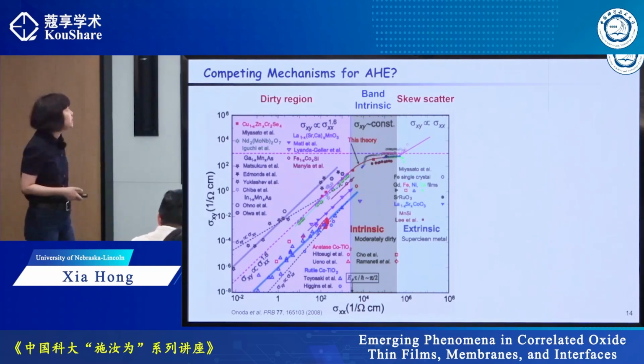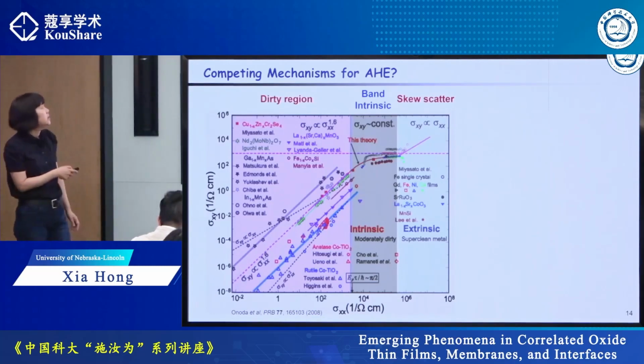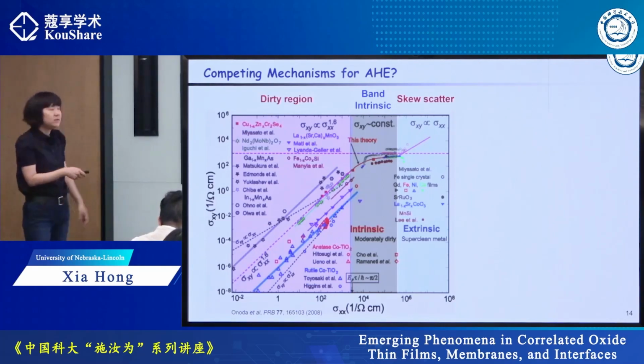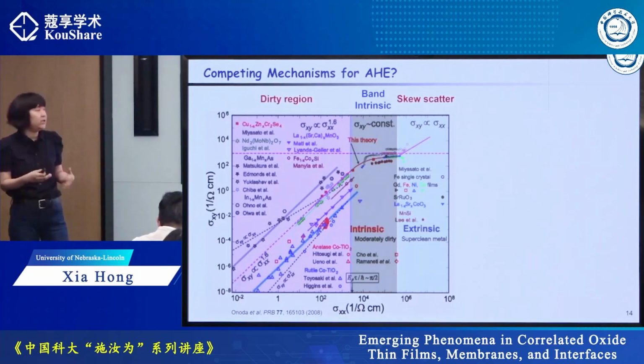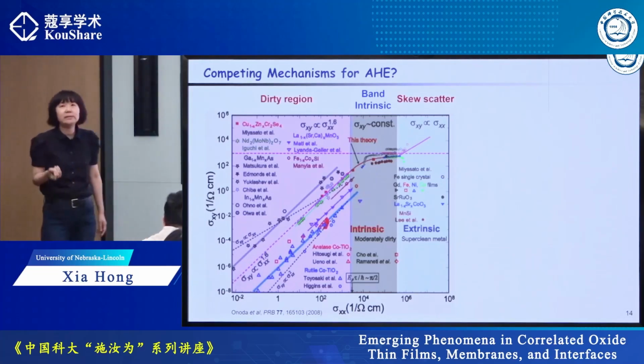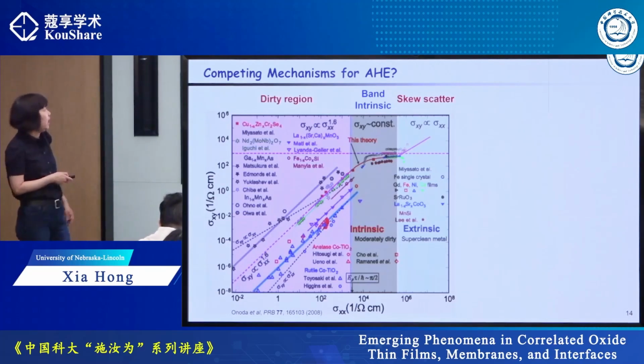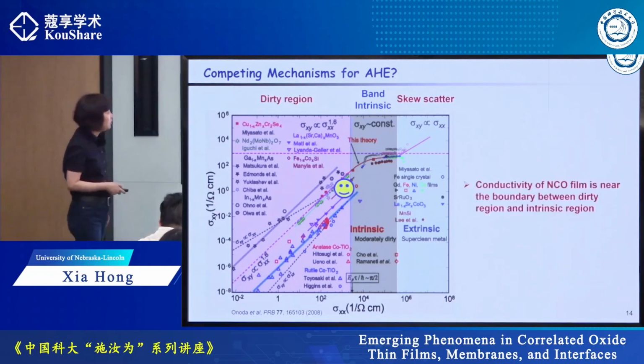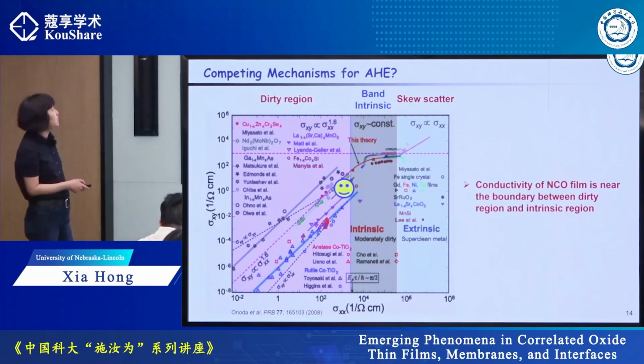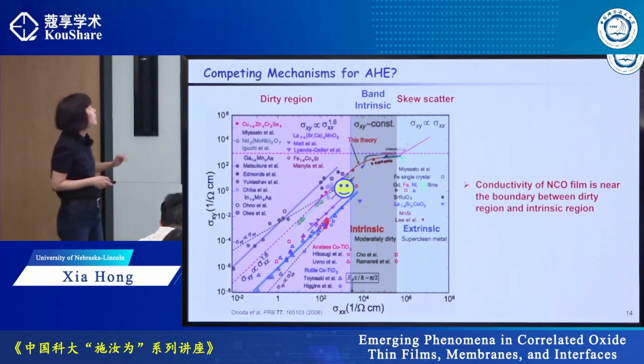If it's a band intrinsic Berry phase effect, then sigma xy is independent of scattering mechanism. So you get a constant. If it's in the dirty region, then your anomalous Hall conductivity is really due to scattering, and it has a power law scaling with power exponent 1.6. And most samples would follow this kind of scaling behavior. And if we look at the sigma xx for our NCO sample, it's right at the boundary between the moderately dirty and the dirty regions.